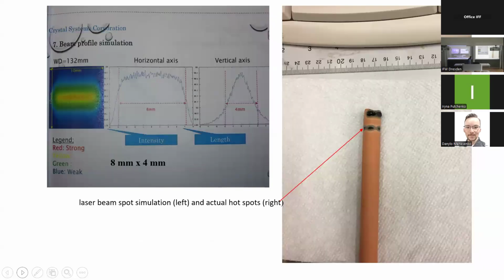So why laser? Each laser has a rectangular beam cross section, vertical axis 4 millimeters by 8 millimeters. Of course, this is a computer simulation, and this is how it looks in reality. These 3 spots were produced by 3 laser beams. The other 2 are on the rear side and not visible. And at least you see that these 3 spots are well vertically aligned.